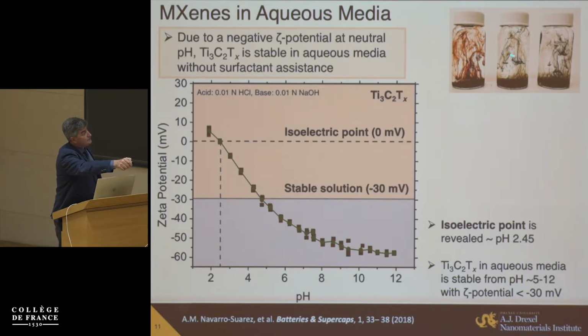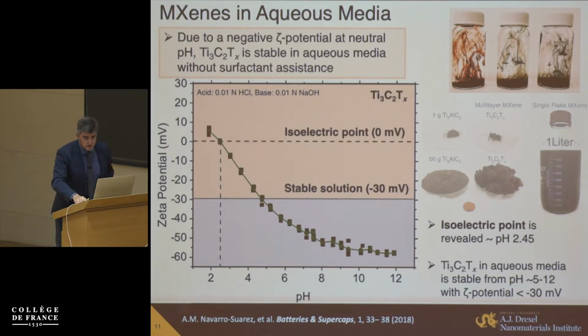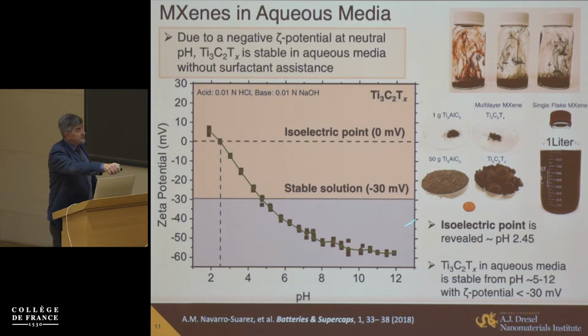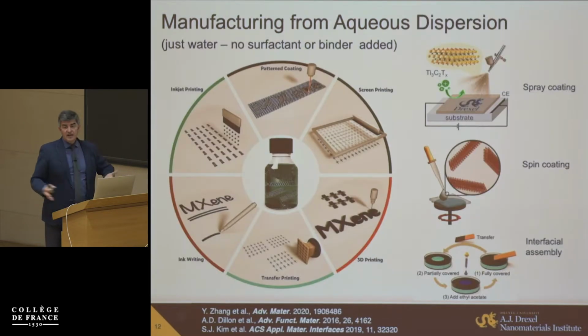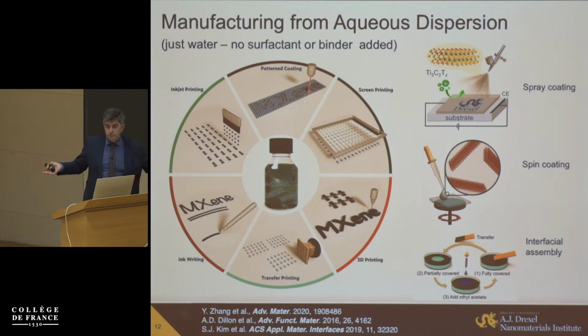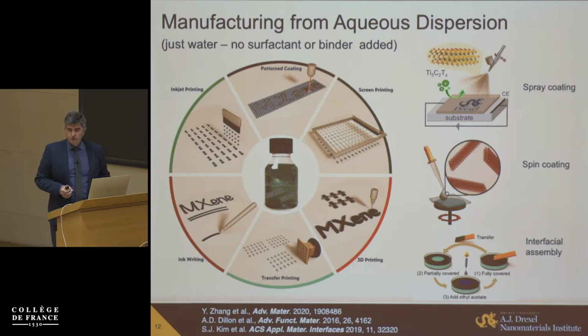And if you put a droplet of different MXene solutions in water, you can see it start dissolving like a dye. You saw how many different colors I showed in the beginning here. So we take MAX phase powder, we etch it, get MXene, and we delaminate it, and this is like a bottle with, I don't know, 10 milligrams per milliliter, say, a usual stock solution of MXene here. So water processable, and if you have a colloidal solution of flakes in water, you can basically do everything people have been doing for decades, if not centuries, with colloidal solutions.